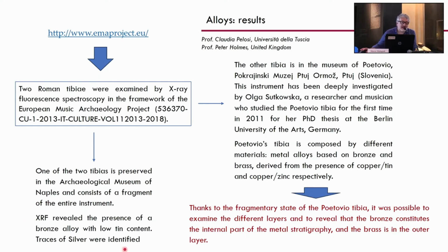And Claudia found there the presence of a bronze alloy with a low tin content. At the same time, she found traces of silver on the materials. But she could analyze, together with Professor Peter Holmes, another tibia from the Poetovio Museum that was studied by Olga Sutkowska, a researcher and a musician, who I think was a PhD student, probably she has already got the PhD. And Claudia obtained results that were ascribable to the presence of bronze and brass at the same time.